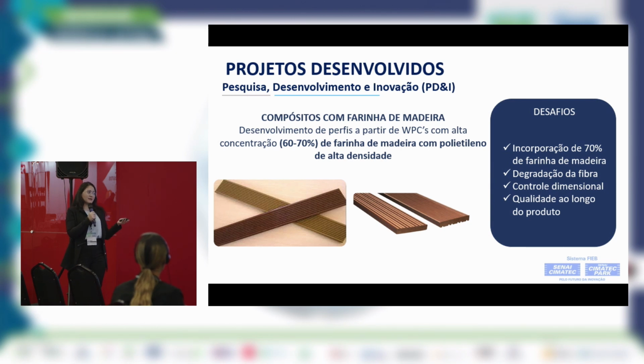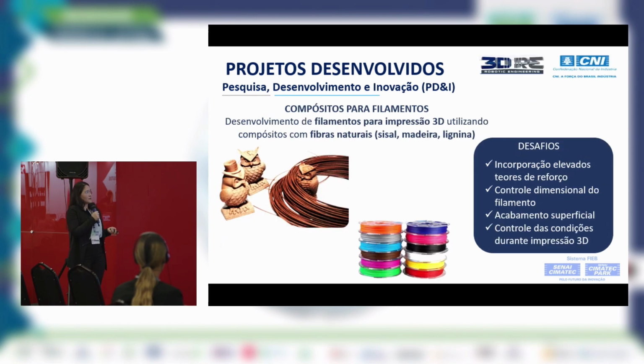Challenges. With 70% of ground wood or wood dust, there is the degradation of the fiber. We need to control the processing temperature because we don't want to see the fiber degraded. The size control, because in order to produce the profiles, we need to really control the size. We want to have the same product being produced throughout. And it's also difficult to maintain the same quality level for the end products.